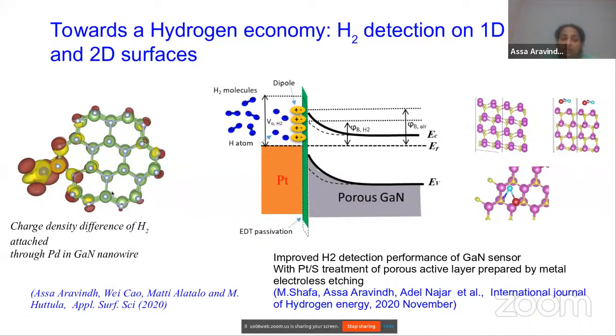Such studies can be performed using DFT, which can guide the experiments and give insight into what can happen. Also, we have another similar study with gallium nitride sensors, which showed enhanced hydrogen detection. We used the same geometry, but in a different way, and we could show very good agreement with the experimental results.